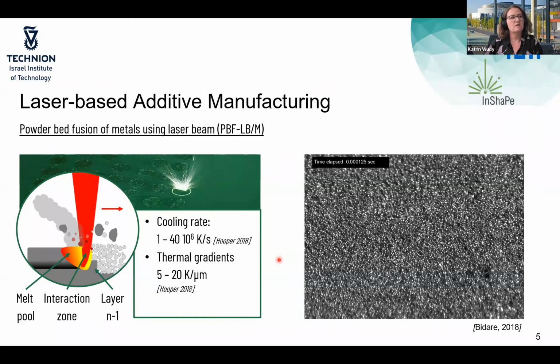So this would be the region we would like to reach at the end for our processing. If we increase the energy input, so we increase the laser power, then you are in a region called the keyhole regime. It's characteristic in this regime that the welding depth is much higher than the width. This is a process regime which is not favored because the probability of creating porosity in our components is quite high in this regime.